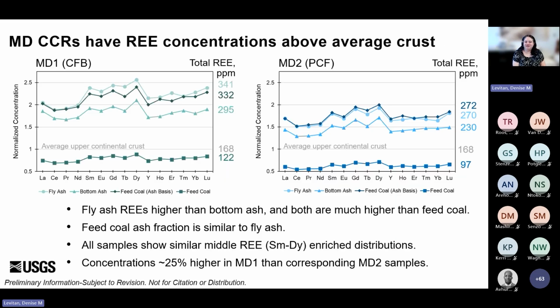So when we look at rare earth element concentrations, there's a few things we see. These are plots of the rare earth element concentrations normalized to average upper continental crust, which we do to make it easier to see. And I have the total rare earth element concentrations listed to the right of each of these plots. Each of these plots has 4 different samples from MD1 on the left in green and MD2 on the right in blue. Going from lightest to darkest, the circles are fly ash, the triangles are bottom ash, the diamonds are feed coal on an ash basis, and the squares are feed coal on a whole coal or total basis. So you can see then that, as we expected, there is rare earth element enrichment in the CCR materials relative to the total feed coal, which are the squares on the bottom.